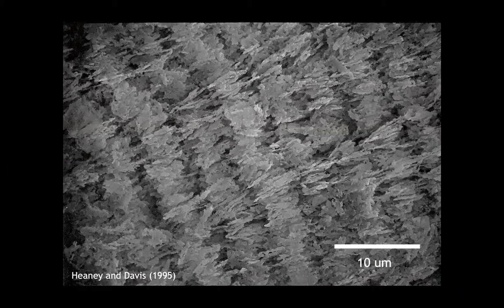When we back off with the SEM to see this texture in an etched agate, you'll note again this kind of hill and valley in the etched agate. We don't see this in a regular thin section agate. I have to etch it with hydrofluoric acid in order to see this texture. But what it reveals is that there's a bimodality to the chalcedony. Some chalcedony is very susceptible to etching, and some is very resistant to the etching. And there is a strict periodicity to the bands that are susceptible and the bands that are resistant. Clifford Frondel wasn't really sure what was responsible for that differential etching behavior.